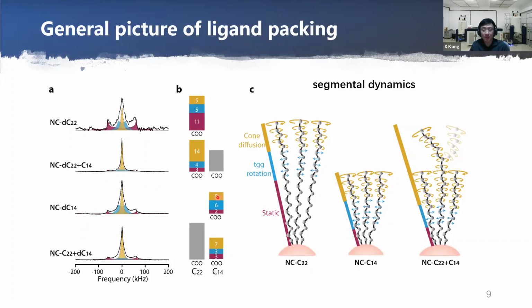From the patterns, we can see the similarities and dissimilarities between the long and short ligands. When they are on pure nanocrystals, the outer 5 units are free for both long and short ligands. But when the two ligands are mixed on a single nanocrystal, the outer 14 units become free for the longer ligand. But the changes in the shorter ligand are relatively small. Based on these results, we can make a schematic illustration of the ligand layer on this nanocrystal.